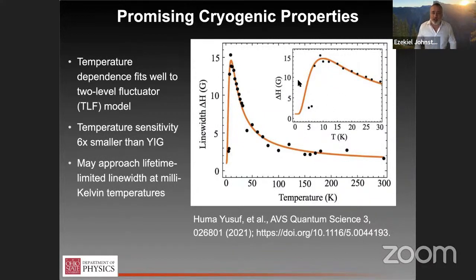And what happens is at very low temperatures, the coherence time of those spins gets to be long enough that they're essentially synchronized and phase locked to the magnon excitations, at which point they can, again, no longer efficiently scatter magnons. So this is why you see this dramatic drop in the damping at low temperature. So this is to 5 Kelvin because this is what's easy to do with bulk samples. We're working with our collaborators at Cornell to get these measurements into the millikelvin range.